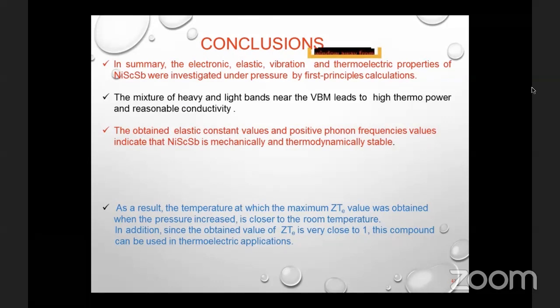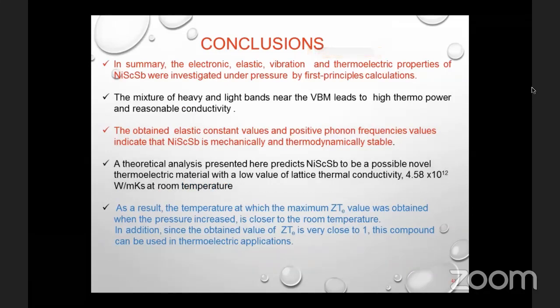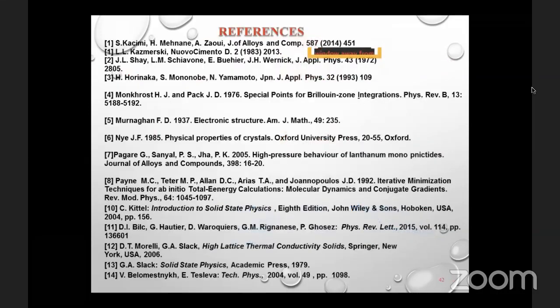As a result, the temperature at which the maximum ZT value was obtained gets closer to room temperature when the pressure increases. In addition, since the obtained ZT value is very close to 1, this compound can be used in thermoelectric applications. To sum up, we hope that our theoretical calculated results may help experimentalists. These are references, and thank you for your attention.